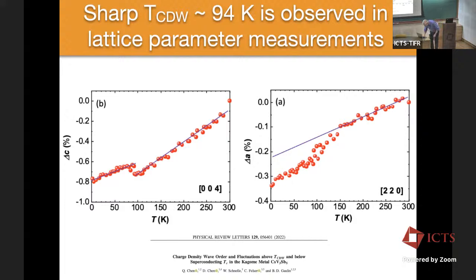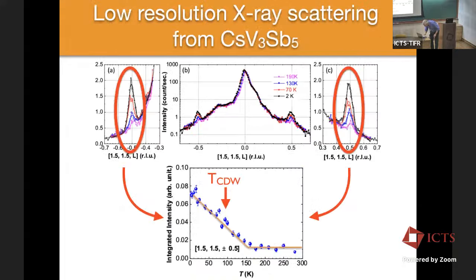But the actual measurements of the Bragg-like features that correspond to a doubling of the unit cell in the Kagome plane and a doubling perpendicular to the Kagome plane, that's these intensities here, and there's nothing special about 94 Kelvin there. That's right. In fact, that's the main conclusion.